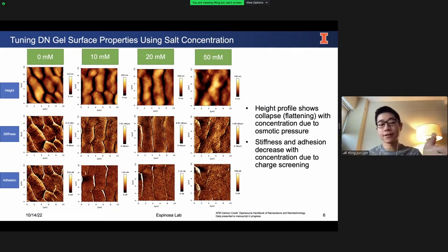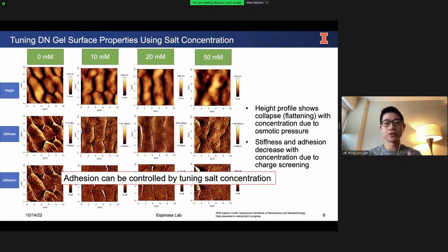Next, let's look at the stiffness and adhesion channels. And the stiffness and adhesion are also generally decreasing with the increase in salt concentration. And I believe that this is due to charge screening. And I'll talk more about charge screening in the next slide. Importantly, what I want to show you with this series of AFM images is that adhesion of hydrogels can actually be controlled if we tune the salt concentration that we immerse them in.